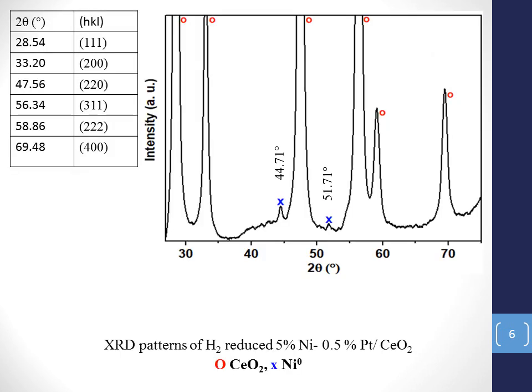The XRD pattern of 5% nickel, 0.5% platinum deposited on CeO2 powder showed a cubic crystal structure of the support. The most intense diffraction peaks and their corresponding diffracted planes are presented in the table. The crystallite size of CeO2 calculated using the Scherrer relation is about 10 nanometers. It also shows the appearance of two new peaks with low intensity, indicating the presence of a nickel metallic phase.